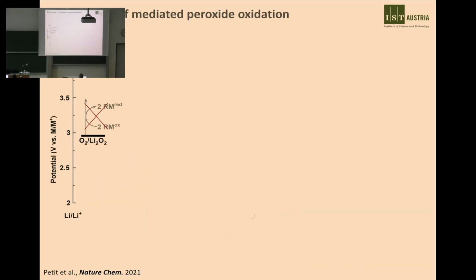We looked closely into this mechanism. First we have shown that the direct concerted 2-electron mechanism is not happening; it is extremely unlikely. What really happens is that a first equivalent of mediator forms a superoxide species at the surface, so you need to think of this as a solid particle. We are extracting lithium ions and electrons, so we have a lithium-deficient surface.